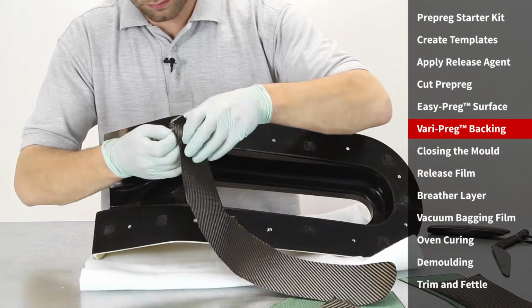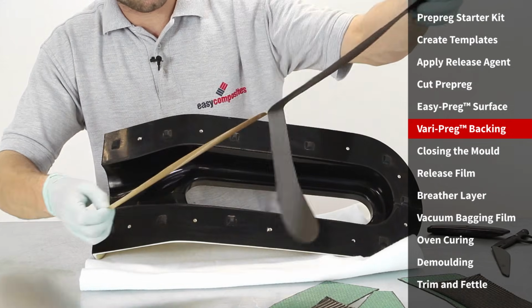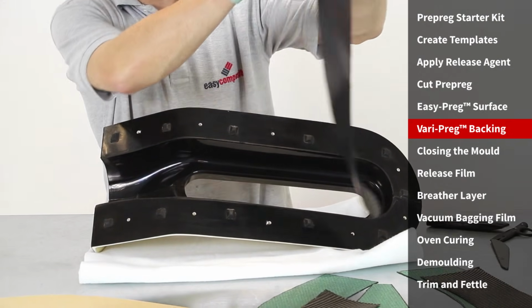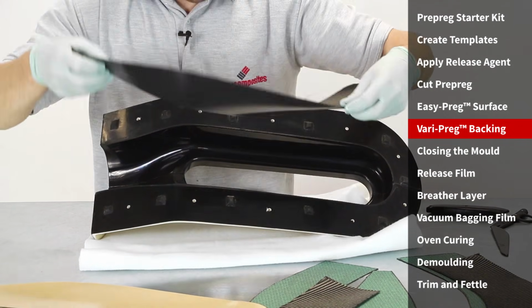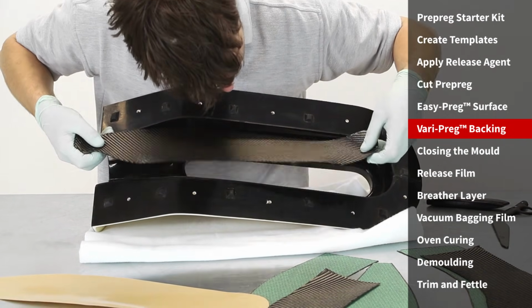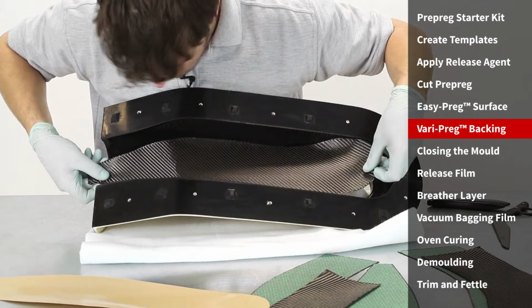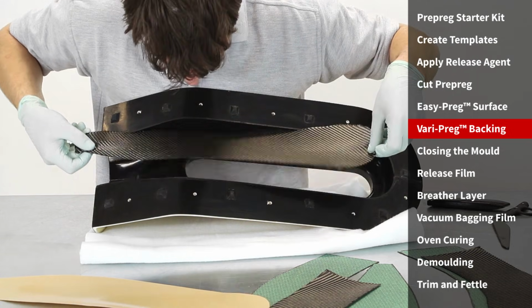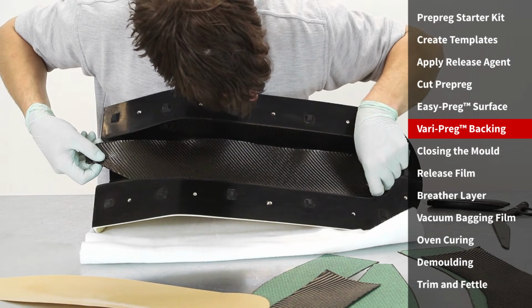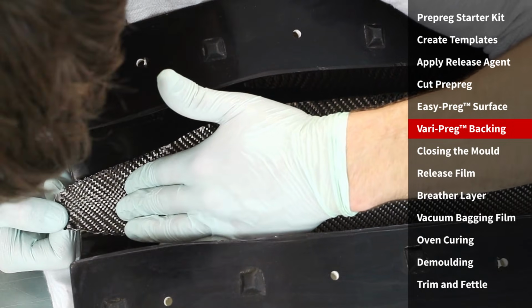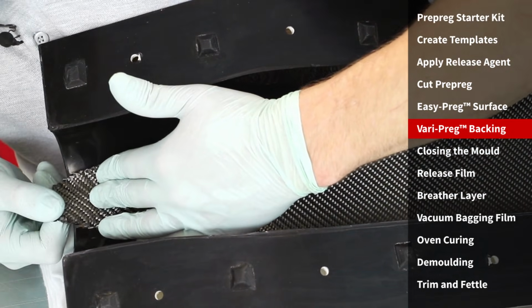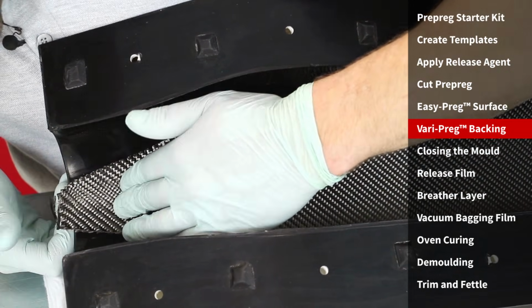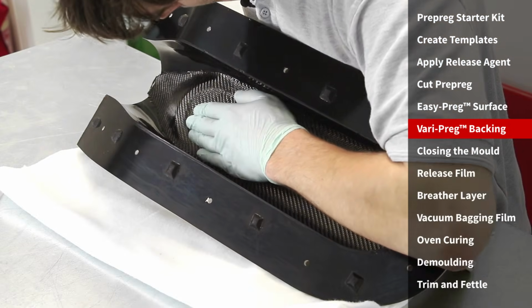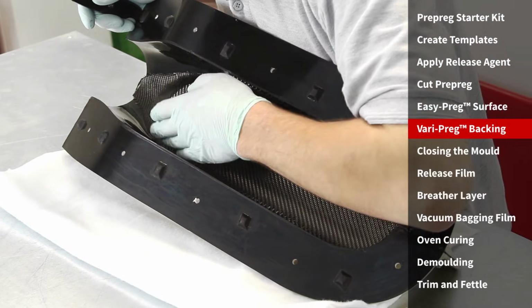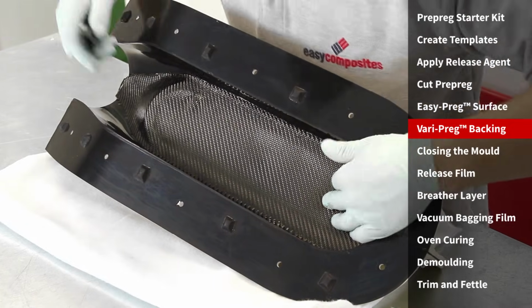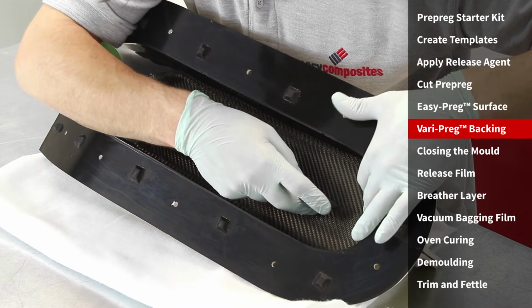With the upper section complete, we will now move on to the slightly more complex layup of the lower mould tool. Starting with the base piece of material, this is laid precisely into the mould. The edges of this piece will be the visible join on the part, so accurate placement ensures a neat final finish. To make handling easier, the hole for the aperture is not cut until the piece is in place. The hole is then simply cut with a knife.